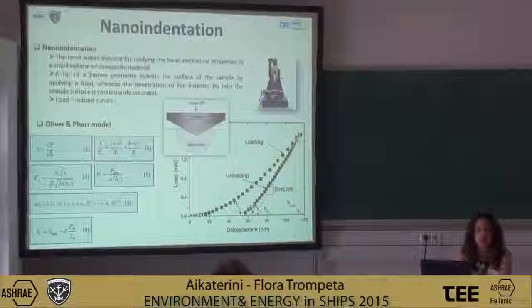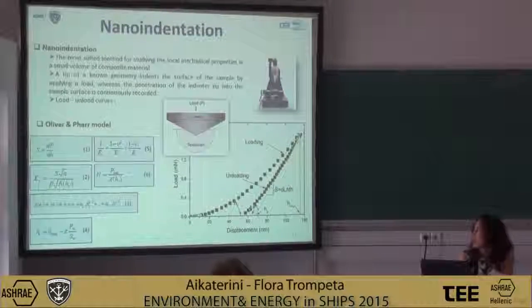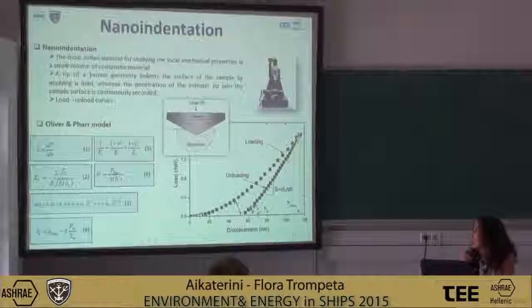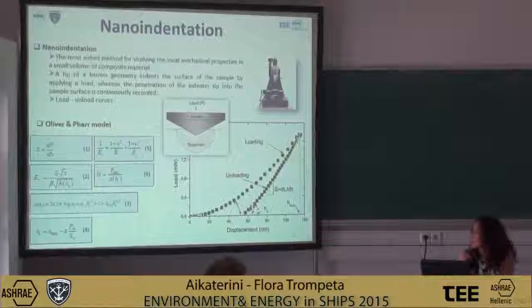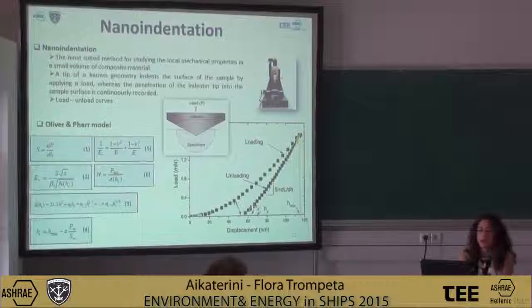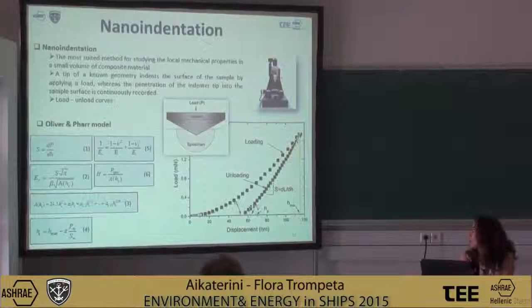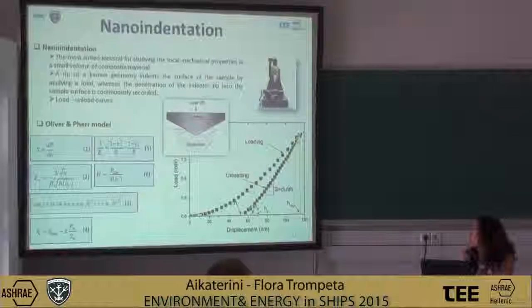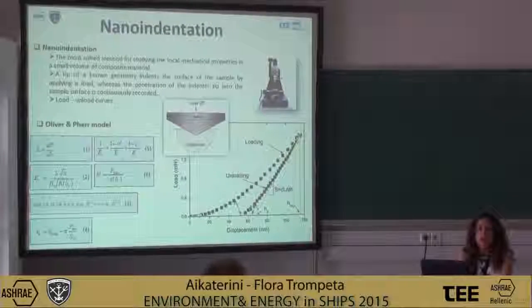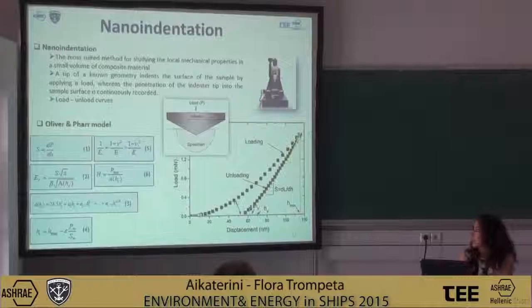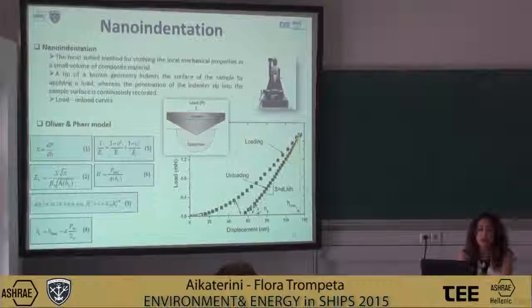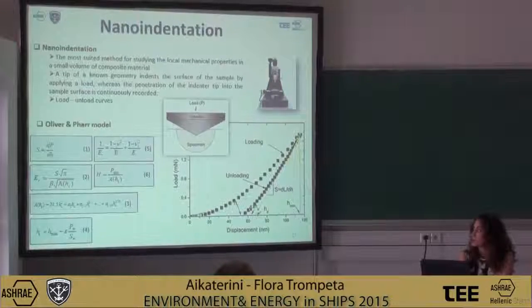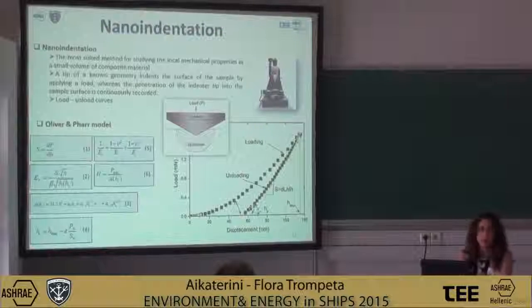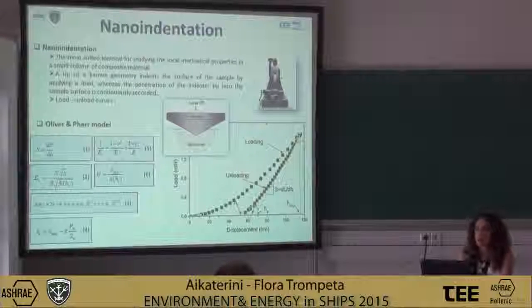The nanoindentation technique is the most suited method for studying the local mechanical properties in a small volume of a composite material. We use a tip of a known geometry that indents the surface of the sample by a standard load, whereas the penetration of the indenter tip into the sample surface is continuously recorded. As a result, we have these load and unload curves, from which we can determine the elastic modulus and the stiffness of the material using the slope of the initial part of the unload curve. After the calculations, we can also calculate the elastic modulus, stiffness and hardness of our material using the Oliver-Pharr model.